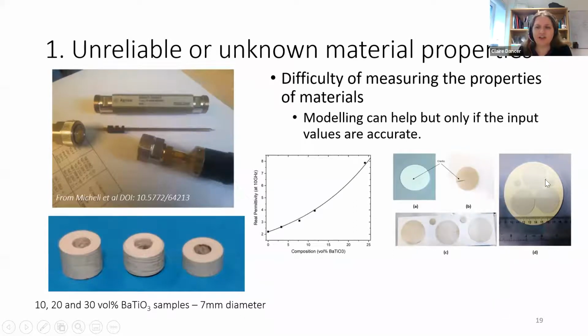So for the work that Abhijit's been doing over the last few years, he's had to be making these very thin sheets of ceramic material. And he probably won't thank me for showing this, but you can see some of his samples have sadly cracked during that preparation process. And that's a depressing thing to happen. It's happened to all of us as samples have broken, but it's because you get this warpage in the material. When you're trying to make it so thin, the whole surface of the material will warp during the heat treatment. When you're trying to grind it back to being perfectly flat and parallel, which is what we need to do these measurements and get the accurate values, the chance of it cracking is really quite high. So it's a very difficult thing to do.